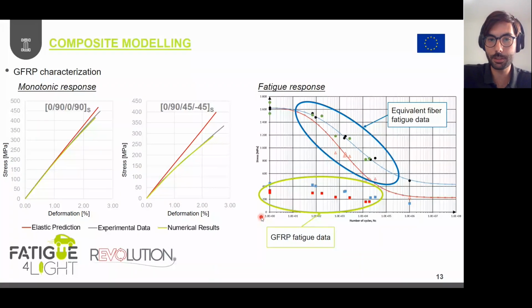Okay, this distribution of layers of this composite, according to that stress level, withstands a certain number of cycles, but we cannot use that. So what we are doing now is transforming this composite information that comes from the experiments to equivalent fatigue of the fiber, which experimentally is the one that is experiencing fatigue. And then we calibrate to fatigue the fiber in order to, thanks to the serial parallel, obtain the proper fatigue life of the whole composite material. But this is work in progress.